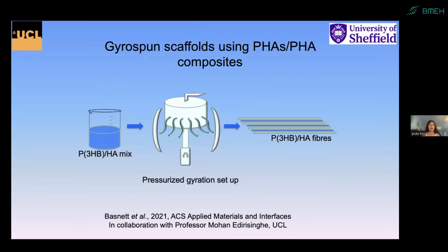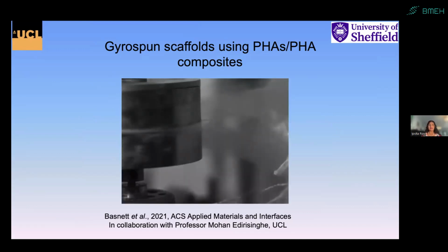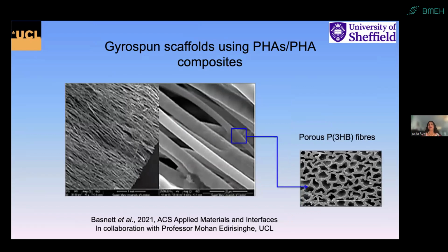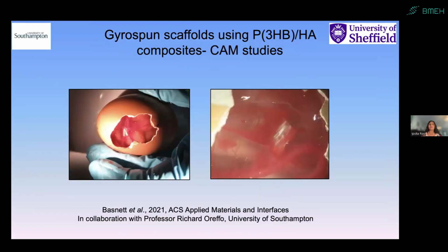This is gyrospun scaffolds that were produced with P3HB and hydroxyapatite. The fibers were produced, as you can see here, with a rotating cylinder, and the fibers are gyrated out of the cylinder. And you can see how beautifully aligned these fibers are, nice and porous in nature. And when we did some egg studies, which is an ex ovo study, these are called the CAM studies, to determine the biocompatibility and the vascularization of these gyrospun scaffolds, we obtained beautiful results.